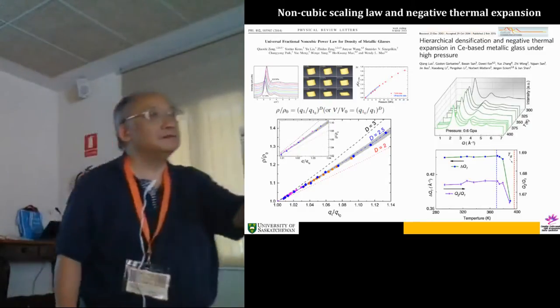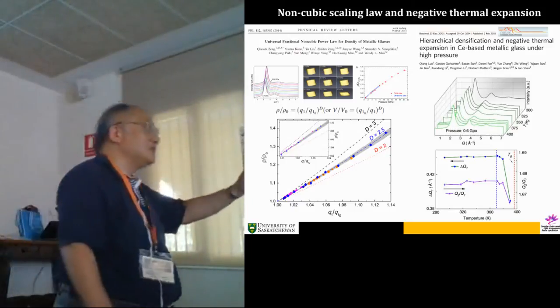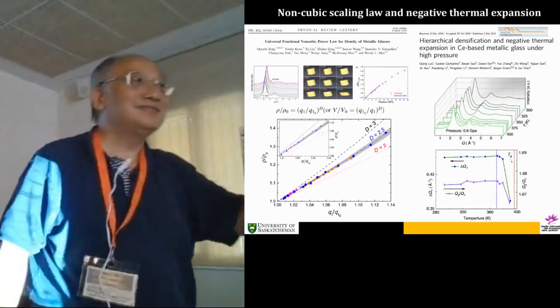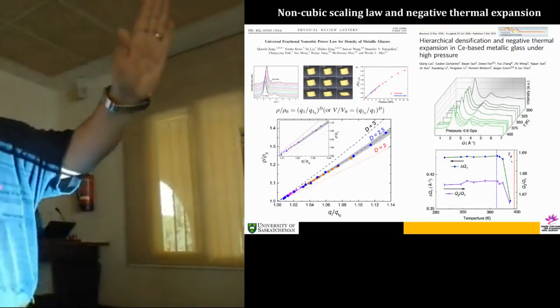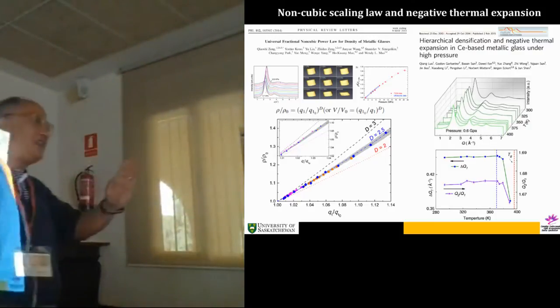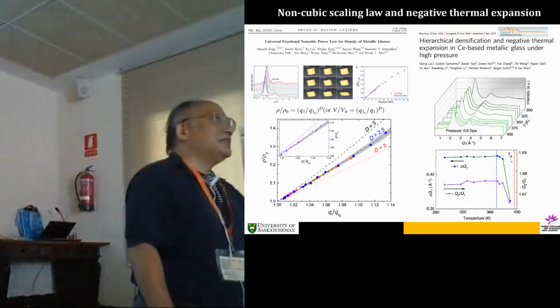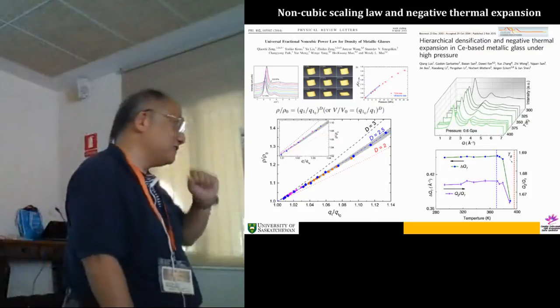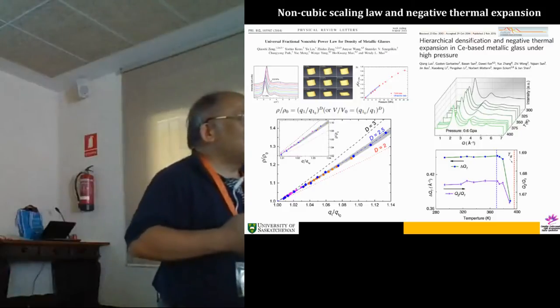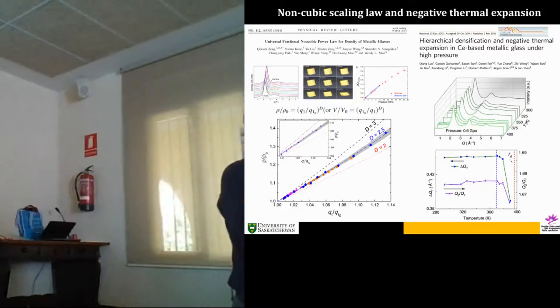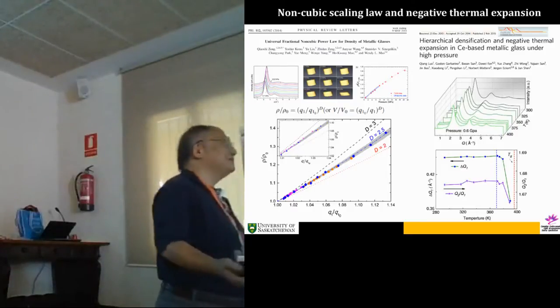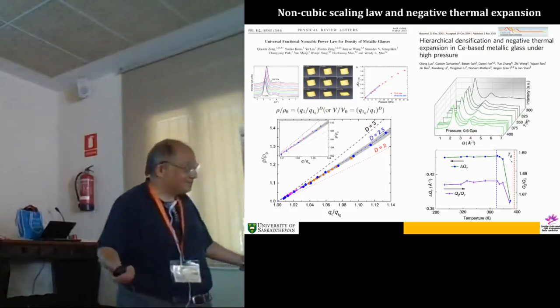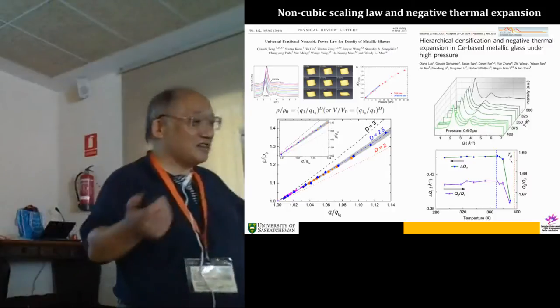They tell you something. So what's the difference between a crystal and an amorphous solid? A crystal has long-range ordering, whatever long-range means. All right? A glass are intermediate to short-range ordering. You can go from a glass to a crystal telling you pressure somehow have an order parameter you can control and go from glass to the crystal. Think about another way. From the crystal back to glass, it tells you something about how glass form and what the glass structure is. It's fairly fundamental to understand glass, right?